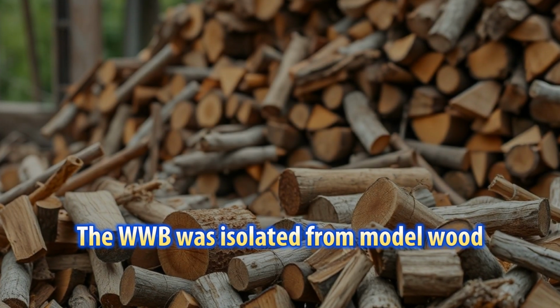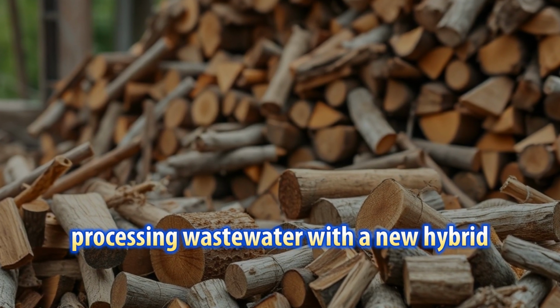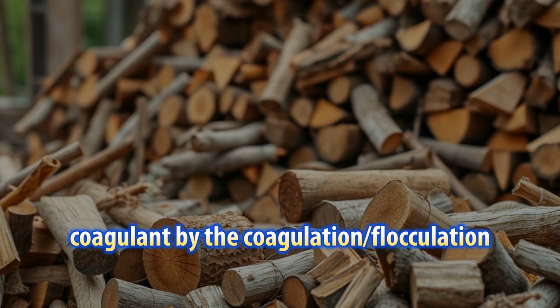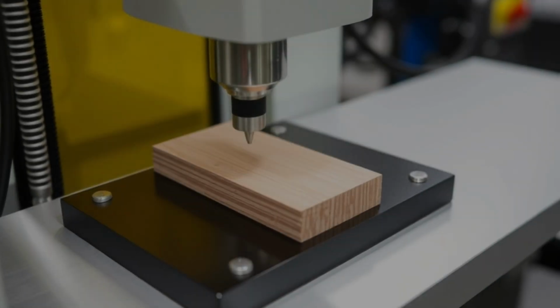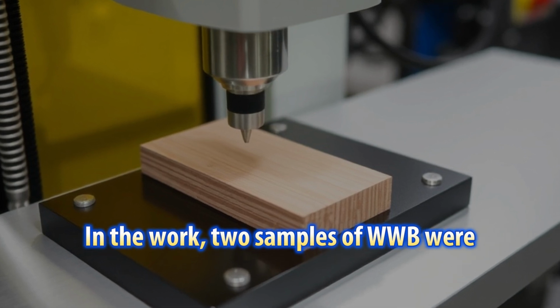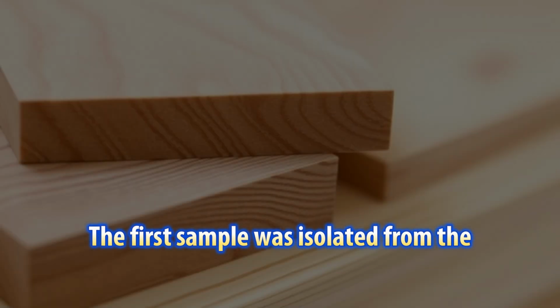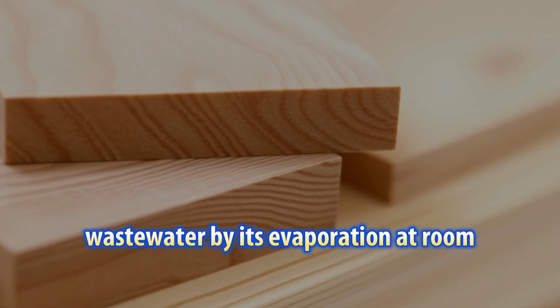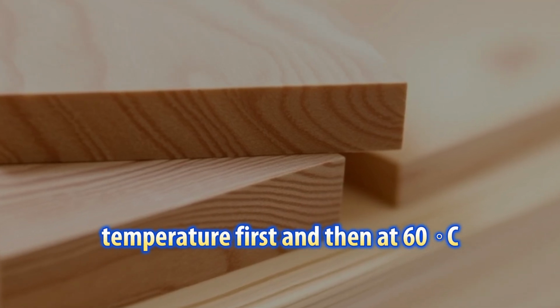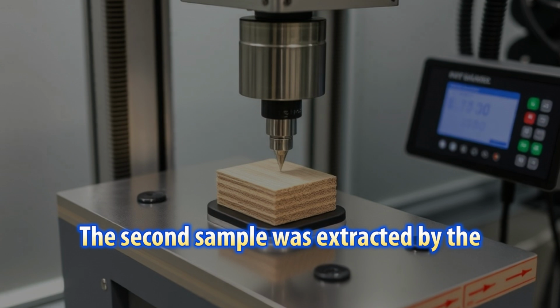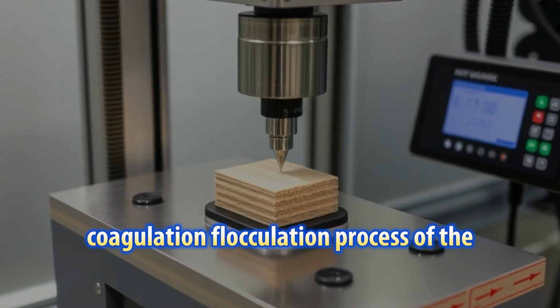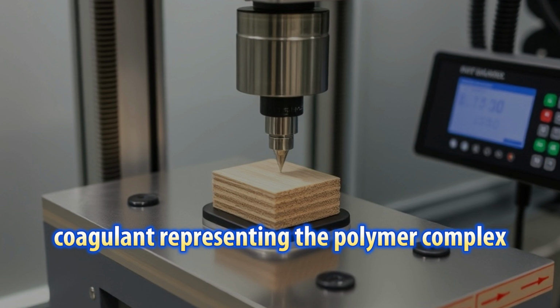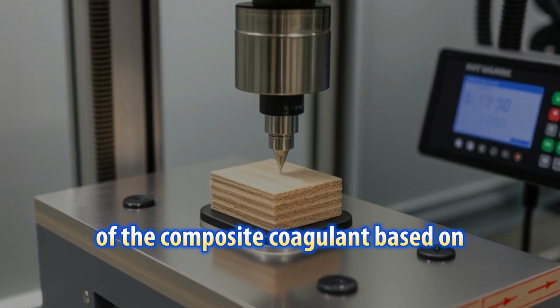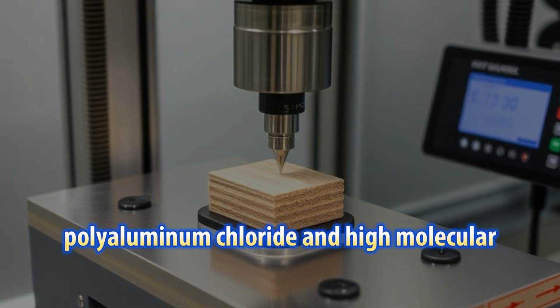The WWB was isolated from model wood processing wastewater with a new hybrid coagulant by the coagulation flocculation method. In the work, 2 samples of WWB were studied. The first sample was isolated from the wastewater by its evaporation at room temperature first and then at 60 degrees Celsius for 48 hours. The second sample was extracted by the coagulation flocculation process of the wastewater with the developed hybrid coagulant, representing the polymer complex of the composite coagulant based on polyaluminium chloride and high molecular polyethylenamine.